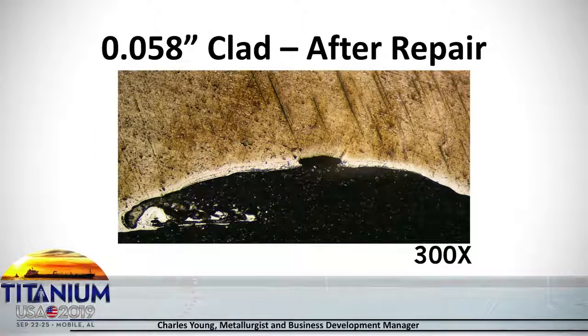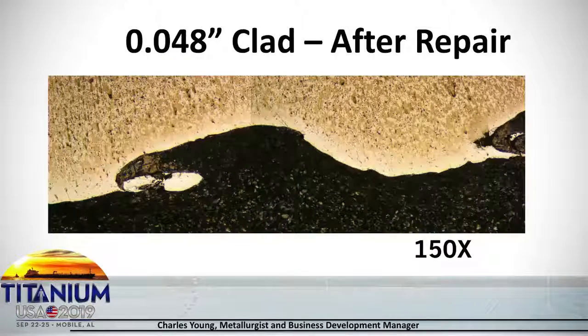048, you're seeing, again, disruption in this area. This area you can't really see that well, but you see disruption here. And if you look at it under the microscope, again, you're seeing this white area here is your oxide, and you're starting to get probably a little bit of diffusion of the steel or the iron into the titanium, which is going to cause you problems.